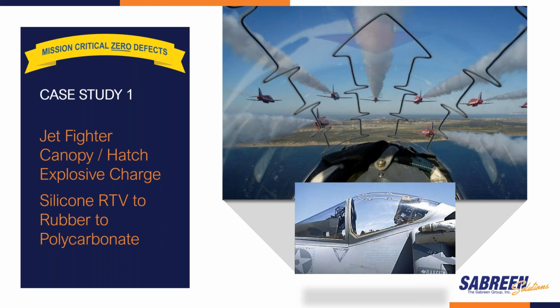In the first case, this is technology that's used in all jet fighters, and what we're trying to do is adhere the hatch explosive charge to the canopy. In this case, we used a silicone RTV to rubber, and then this is bonded to polycarbonate, and we use classical corona discharge.